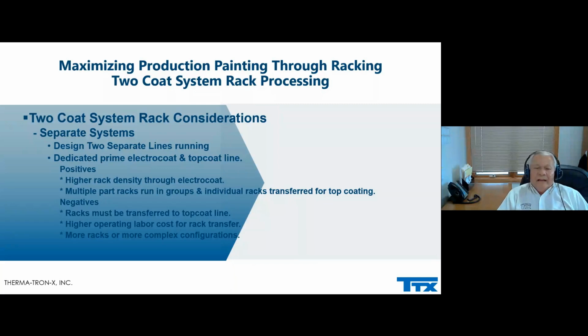There's two ways of thinking on two coat system application for rack processing. Design the system with two separate lines running, where you have a dedicated prime E-coat and topcoat line. The positives on that is a higher rack density through E-coat, which is great. You can separate those. Multiple part racks can be run in groups, and individual racks transferred to top coating. The negatives are racks must be transferred to the top coat line. The higher labor cost is going to be due to the rack transfer, obviously. There's going to be more racks and more complex configurations for that.